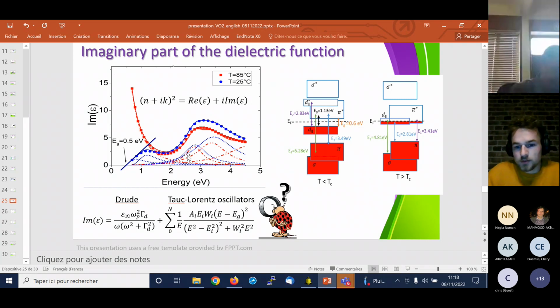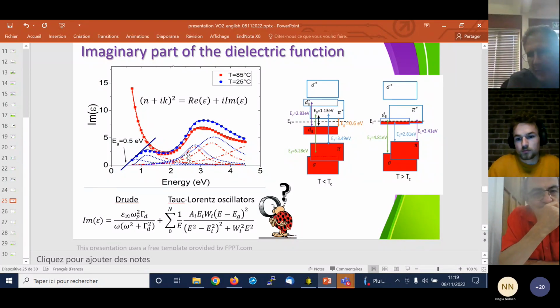Yes, well, we did the reflectivity measurements both in the low and the high temperature phases. And we found out that the thickness was not changing much in this case, because typically those films are quite thin, of the order of 70 nanometers. In fact, the thickness increased by 1 nanometer at high temperature. Even less, yeah, 1 or 2 nanometers.